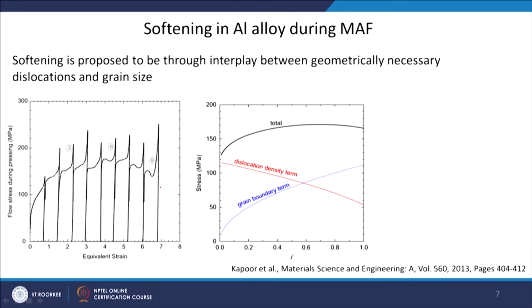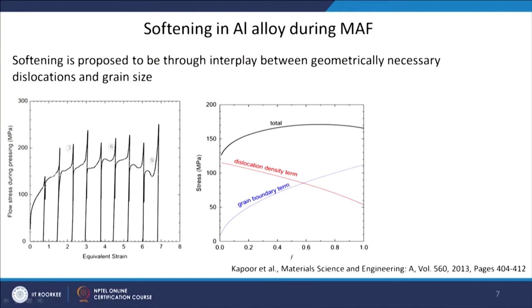And they have attributed this change in the flow stress to these two terms. When you are deforming, of course you are increasing the dislocation density in the material. But if a recrystallization process is also going on simultaneously, there will be refinement in the grain size. So the grain boundary effect is increasing, whereas the dislocation density is decreasing. Dislocation density contributes to work hardening or strain hardening, and grain boundaries contribute through the Hall-Petch relationship.